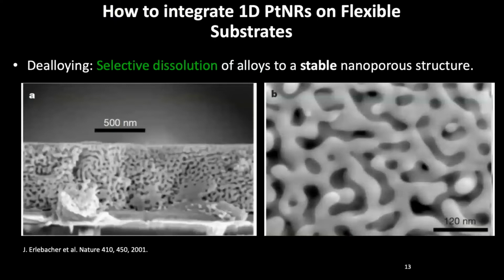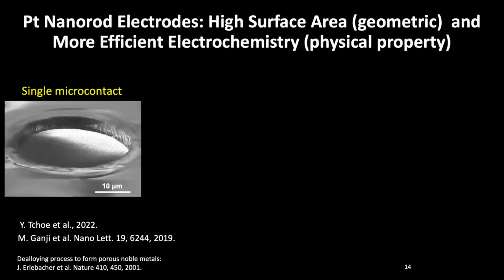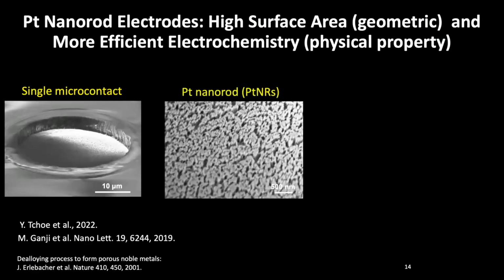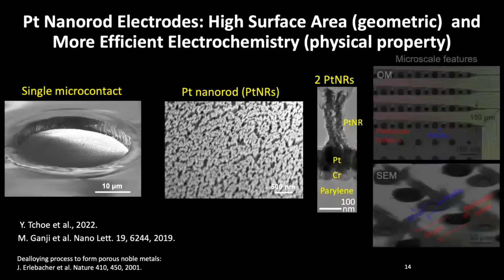So gold and silver were co-sputtered, and then they were inserted in a hot nitric acid bath where silver can be selectively etched away. And to minimize the surface energy, gold then diffuses to the surface, and this process continues until you get a nanoporous structure. So we optimized this process in order to make platinum nanorods. This is the single contact, and the rods are recessed in the contact below the surface. If we zoom in, we can see a mesh of platinum nanorods made with this process.